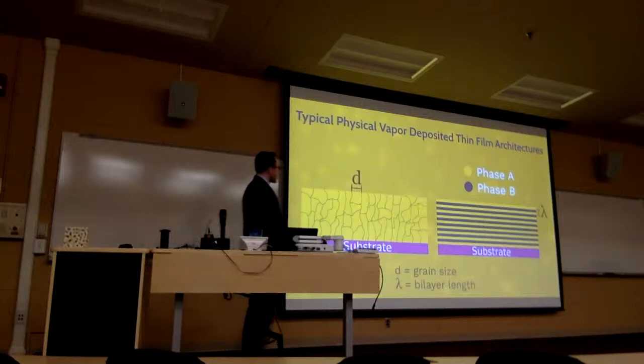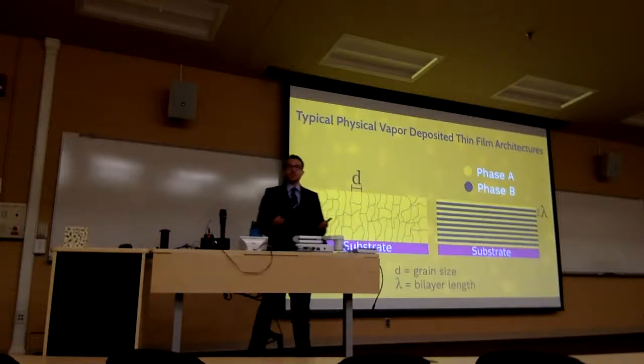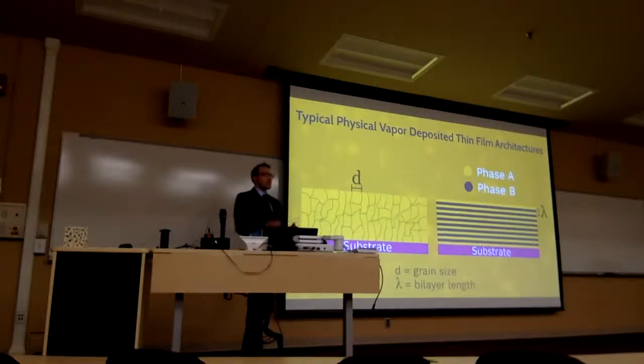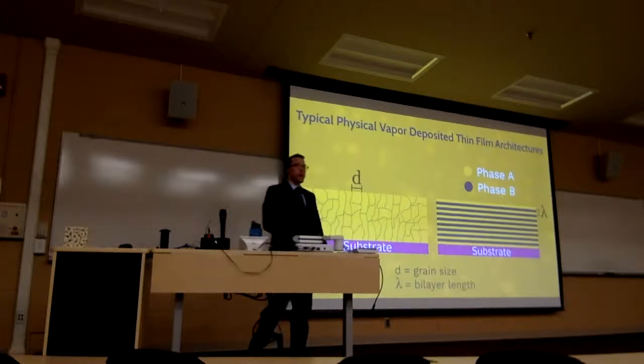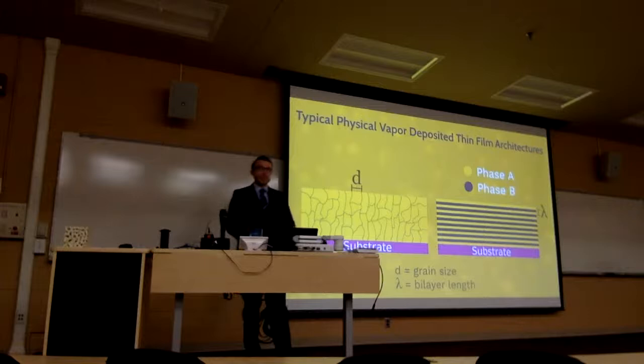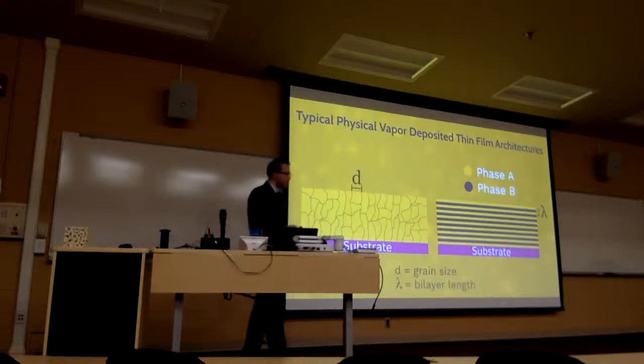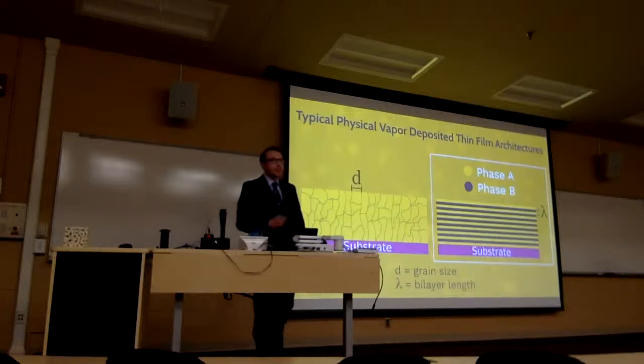So typical thin film architectures look something like this. On the left, you have a fairly simple case where we deposit a material onto a substrate, and it might have some grain structure that we can describe with one length scale D. That's the grain size of that material. Another material is actually a composite of two or more materials that we've layered sequentially in a multi-layered stack. We can also describe this with one length scale, lambda. And this is the bilayer length scale for that material. Now, this material on the right, this nanocomposite, is a very interesting material as it has interesting mechanical properties. I'll tell you why right now.